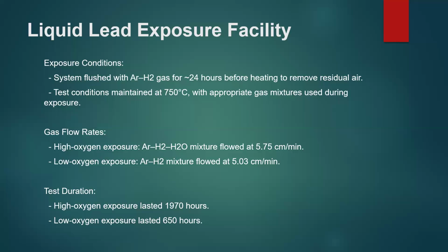For the test duration, the high oxygen exposure test lasted 1970 hours, and the low oxygen exposure lasted 650 hours.